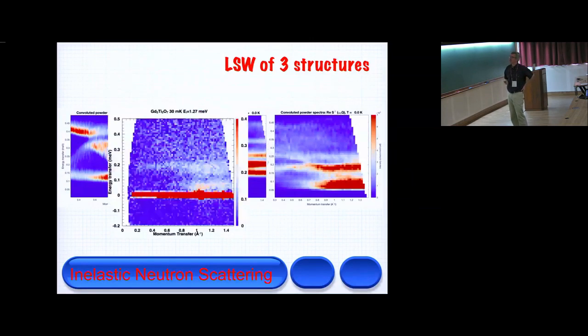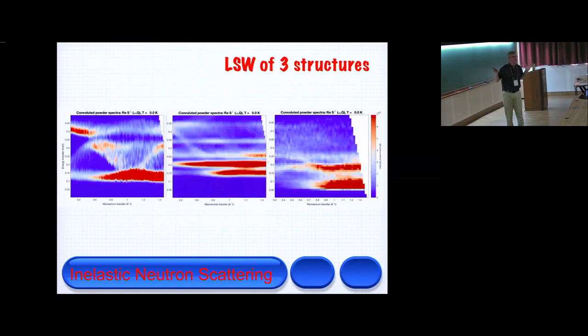So if I go back to the data, I've covered up the other 2 because I want to try and convince the readers of a paper soon that this model is appropriate to these data. So there's a flattish band at 0.2, and there's something down here, over here. There's not much up here. So we went through about 30. We just did this by brute force. We're not smart enough to do it any other way. So we went through about 30 different models, doing all the calculations. Each one takes a laptop about 2 days. So you just kept on going.